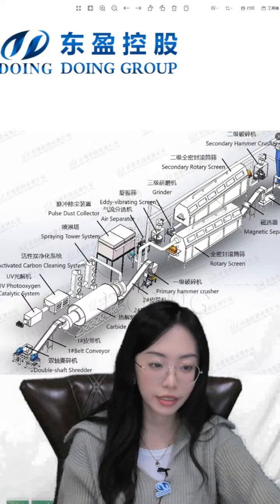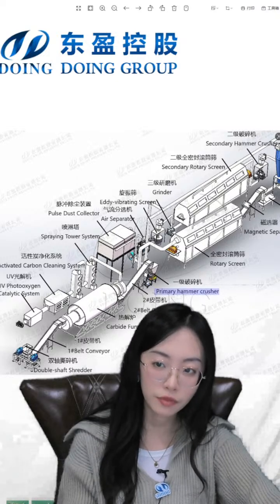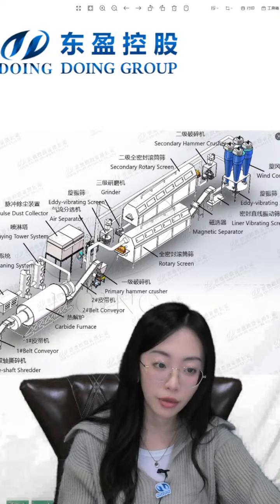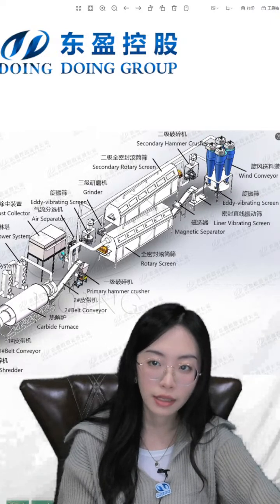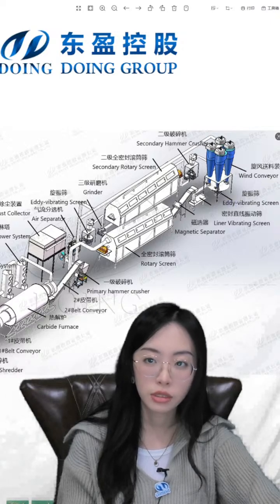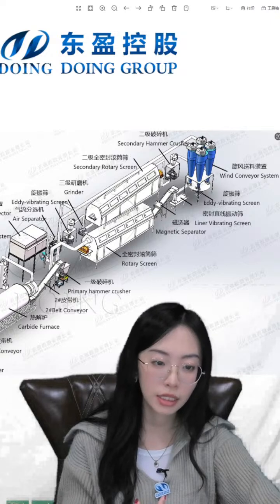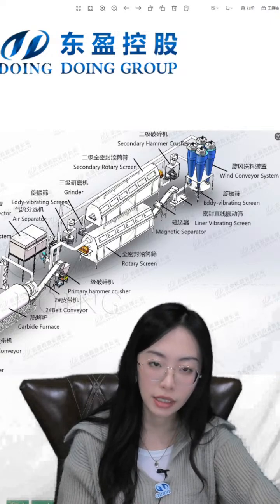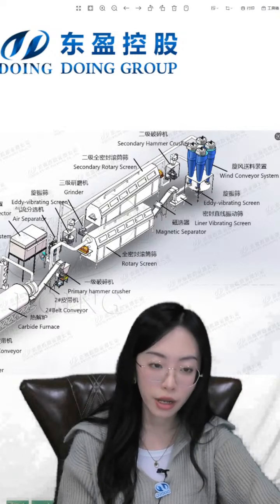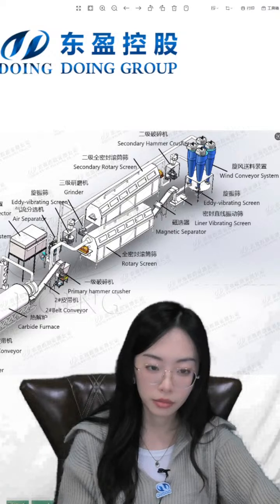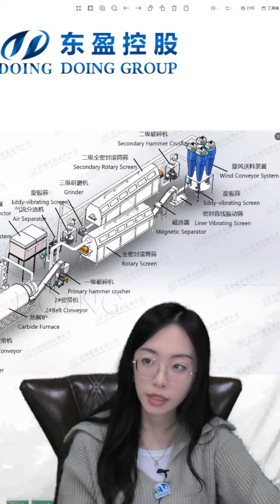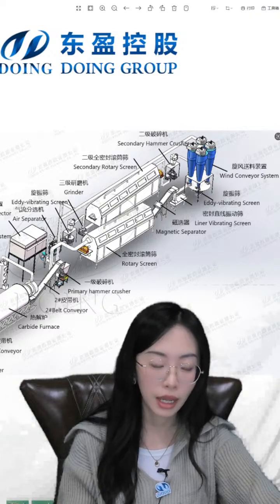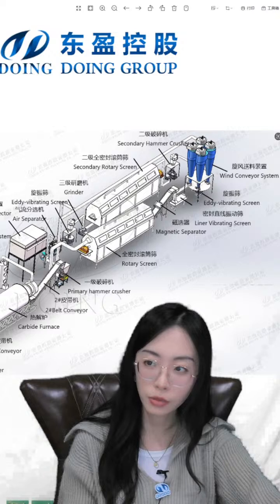And then it will come to the different steps to deeply crush and separate different materials, like the primary hammer crusher, which crushes it to 10 millimeters, and the rotary screen, which recycles 60% of the carbon black. The magnetic separator is to separate the iron inside, and the vibrating screen is to collect the diaphragm and the black powder. Then the secondary hammer crusher crushes the material to 6 millimeters. Then the secondary rotary screen can recycle 90% of the carbon black powder.